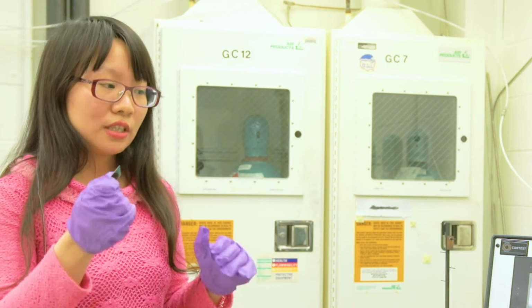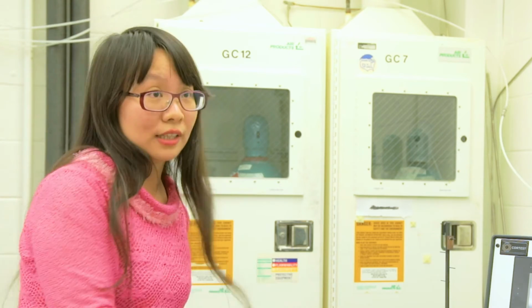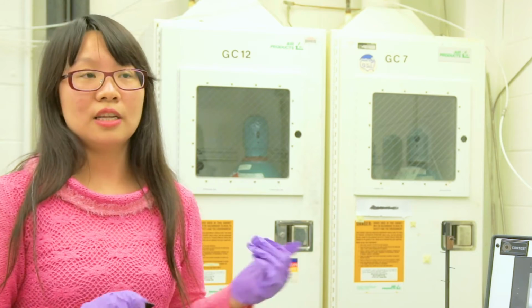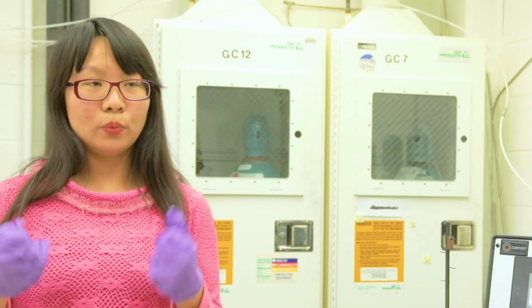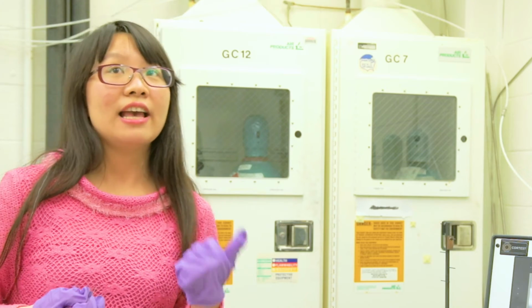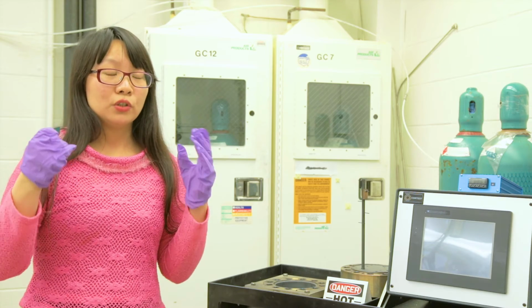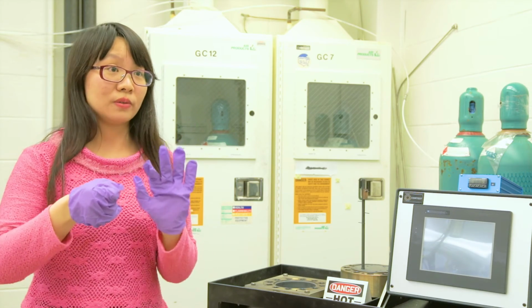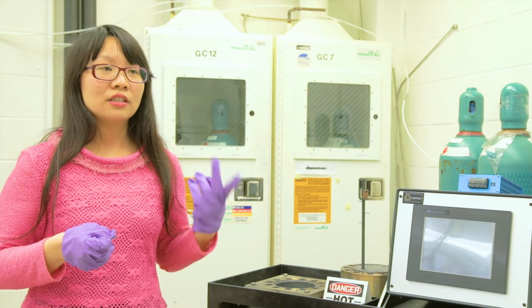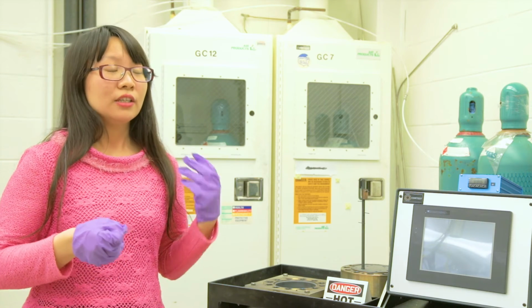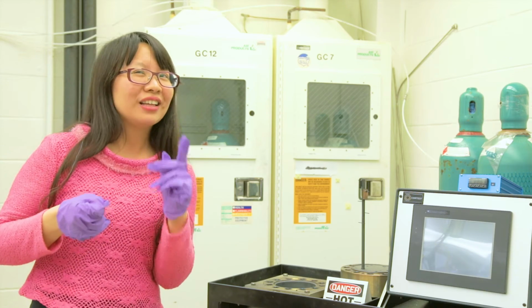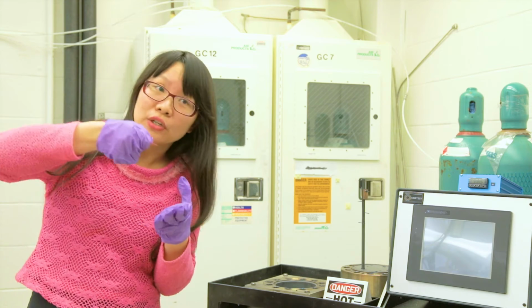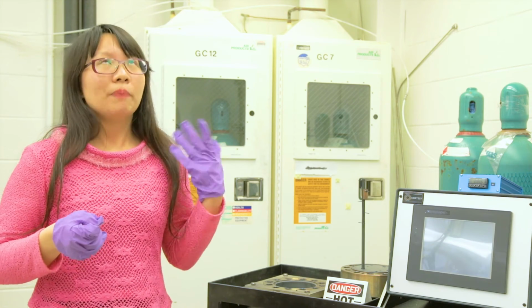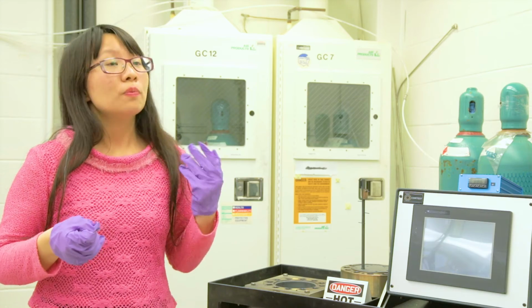After exposing the sample in the autoclave for a certain time, the sample will be taken out. And we will do analysis such as TEM, SEM, or SIMS. We'll use electron microscopy to observe what oxide formed on the materials. And we will use secondary ion mass spectrometry to study how the lithium or potassium cations penetrate into the oxide film, to have a better understanding of corrosion behavior in the new water chemistry.